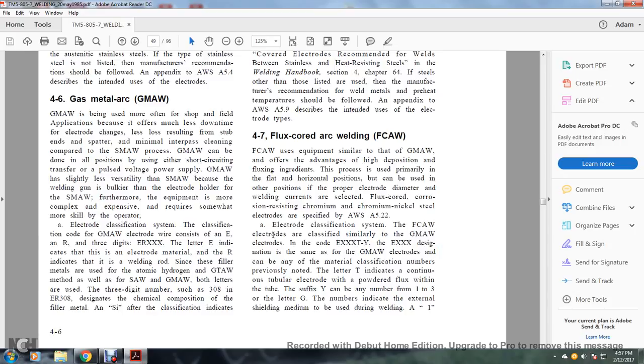Flux cored arc welding electrodes are classified similarly to gas metal arc welding electrodes, encoded in this code: EXXXTY. The EXXX designation is the same as for gas metal arc welding electrodes and can be any of the material classification numbers previously noted. The letter T indicates a continuous tubular electrode with powder flux within the tube. The suffix Y can be either the number 1, 2, 3 or the letter G.